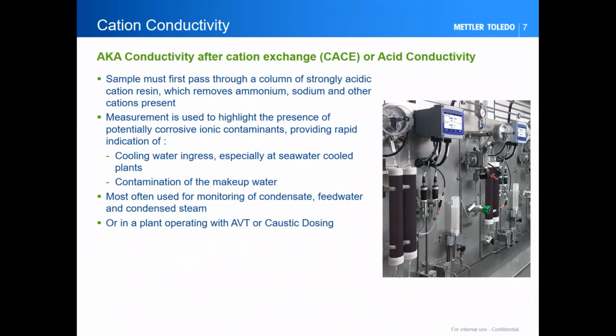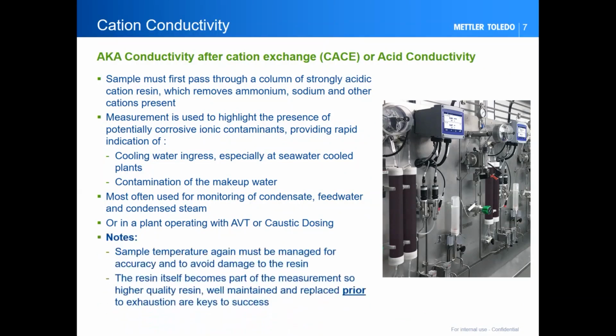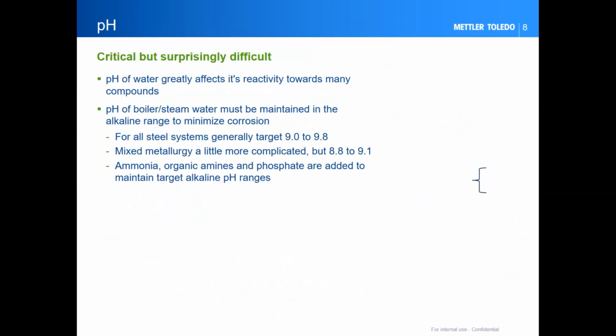Now, the next type of conductivity is cation conductivity, or acid conductivity. One thing you need to think about is that once you're looking at that measurement, the resin column has become part of the measurement. So you need to maintain the sample temperature to avoid any damage to the resin, and monitor the rate at which it's exhausted, particularly if you're running high levels of ammonia, because that resin is going to exhaust quite quickly. Because it's part of the measurement package, the key thing to manage is that you've got to stay on top of resin replacement and regeneration. You don't want it to exhaust and then trip false alarms.